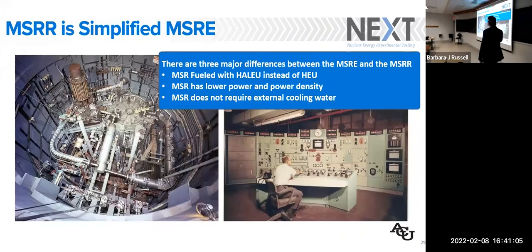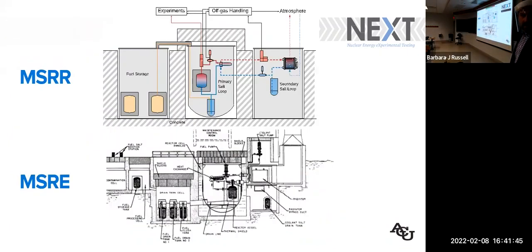So our molten salt reactor experiment is pictured here. That's the Oak Ridge 1965 to 1969 operating reactor. Our molten salt research reactor is modeled after that with basically three simplified assumptions. We're not going to use high enriched uranium because that's a problem. We're not going to strive for as high a power density, so we're actually shooting about an order of magnitude smaller in power density. And our reactor doesn't require cooling water inside the containment, which was their maximum hypothetical accident, what happens if they have a salt water mixture enclosed.